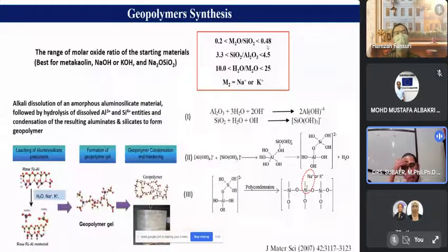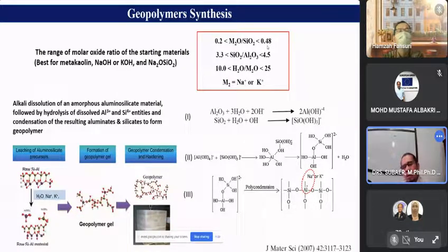We can, of course, take the data from the XRF to see the chemical composition of the starting materials that you use, and then we can adjust the ratio. But because there is a lot of other stuff inside the fly ash or slags, it doesn't always work very well, like when you produce geopolymer from metakaolin. That's why metakaolin was considered a more pure aluminosilicate compared to fly ash or other materials. Anyway, there is a lot of open study in order to standardize the fly ash in the production of